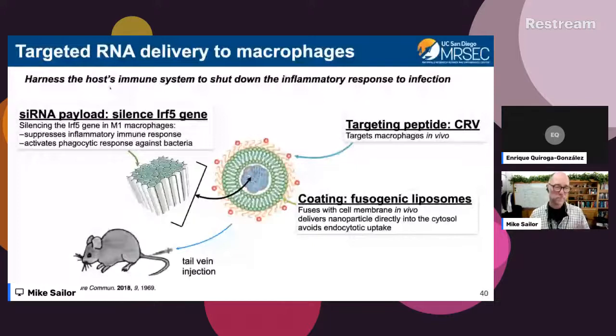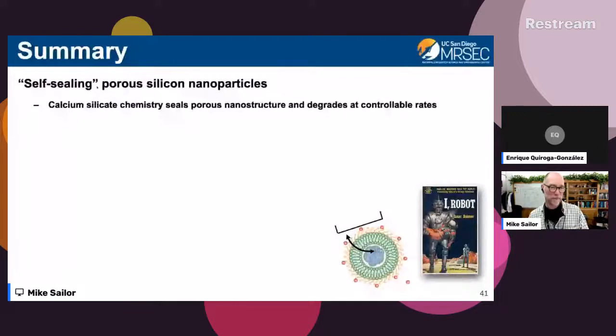So just to summarize everything that we've talked about today, I spent a little bit of time talking about what we call the self-sealing porous silicon nanoparticles. You put these nanoparticles into solution, you squirt in some calcium ion, and they naturally trap anything that happens to be around inside their structure. They dissolve in a very non-toxic fashion. We looked at a lot of cell toxicity, and animal toxicity studies were performed to get to this stage in our studies, and found they're very, very low toxicity.